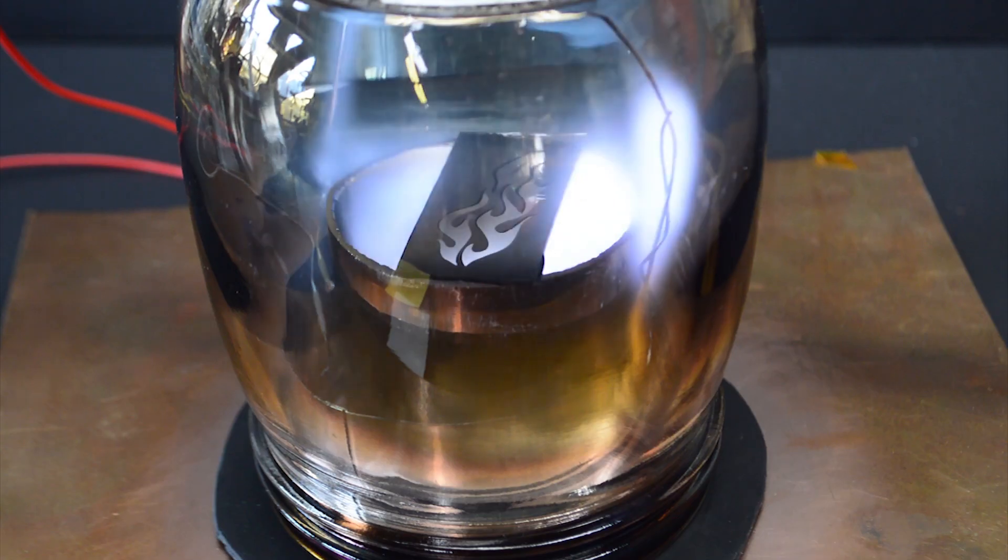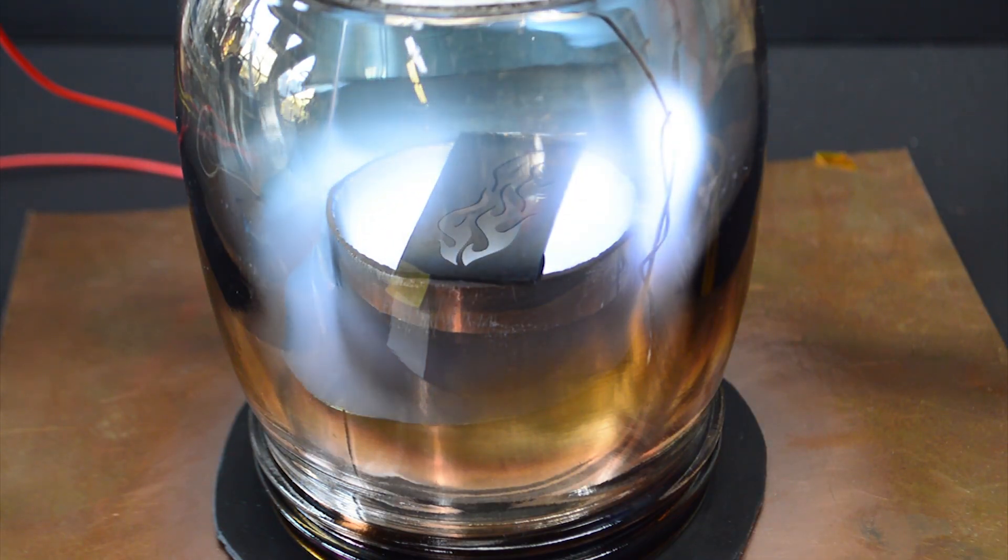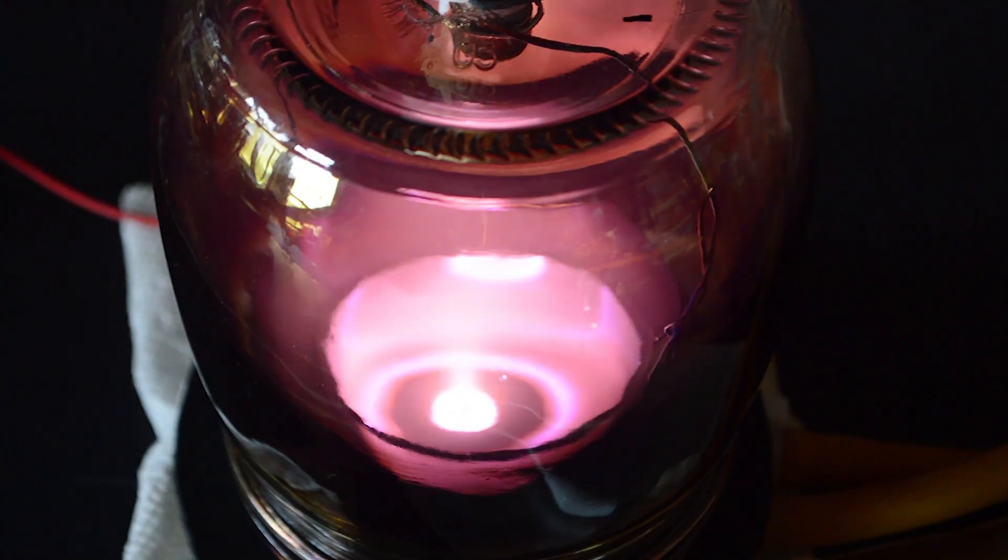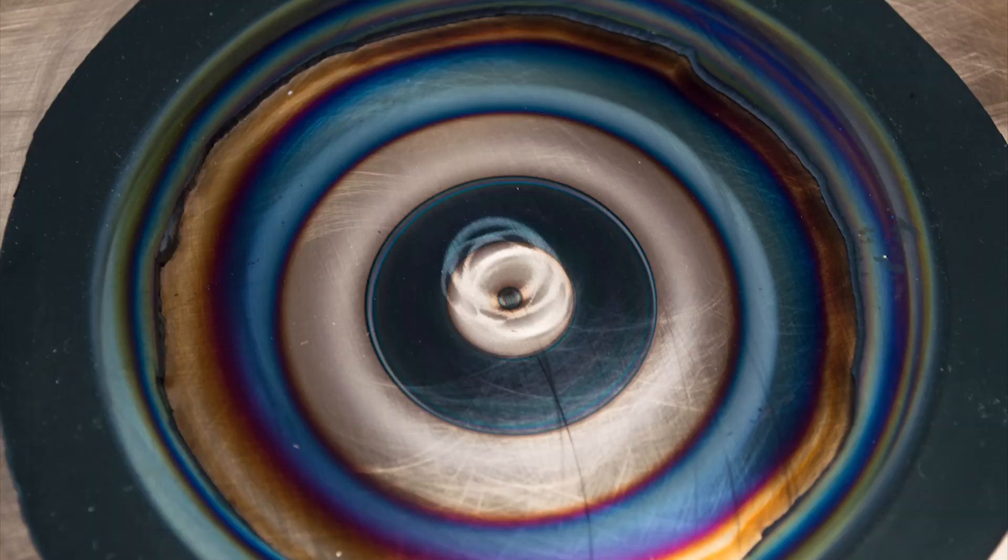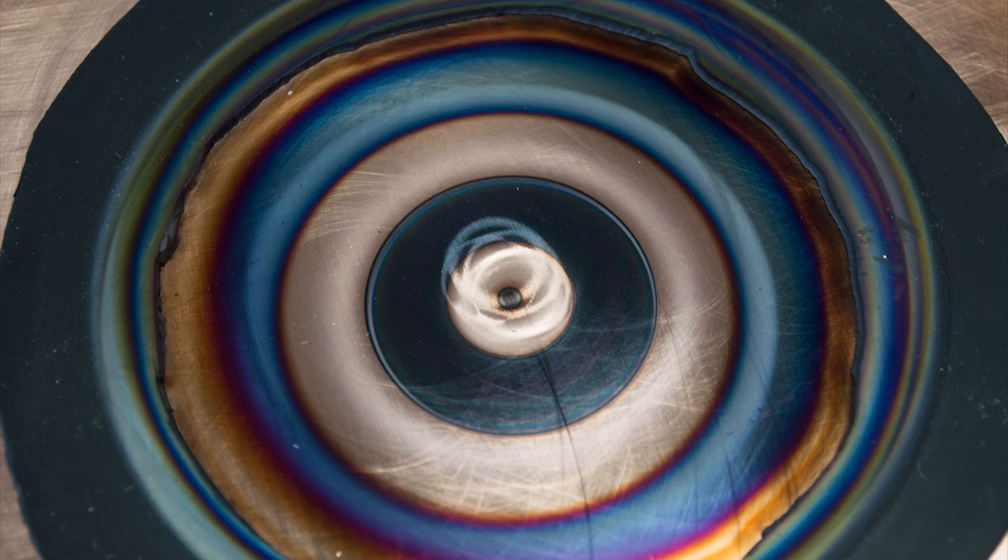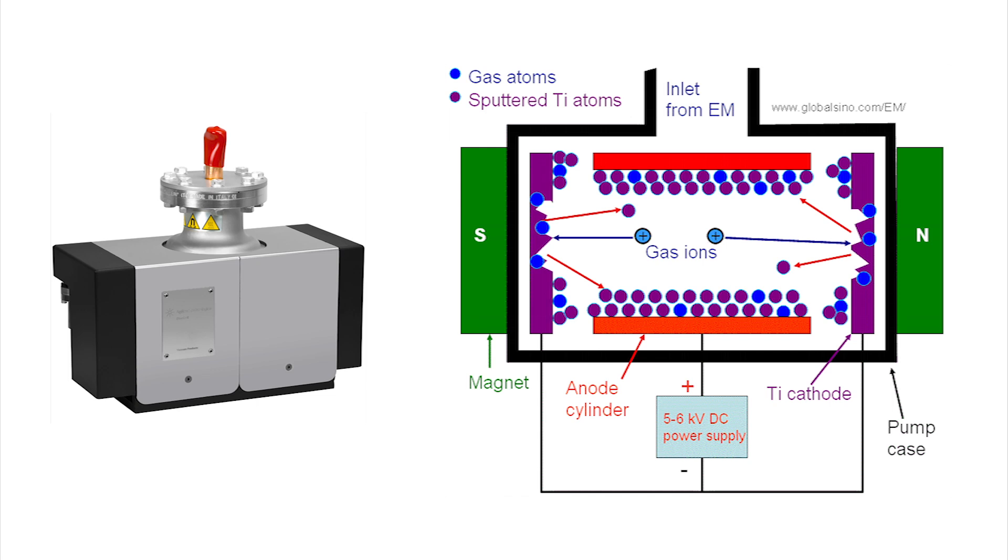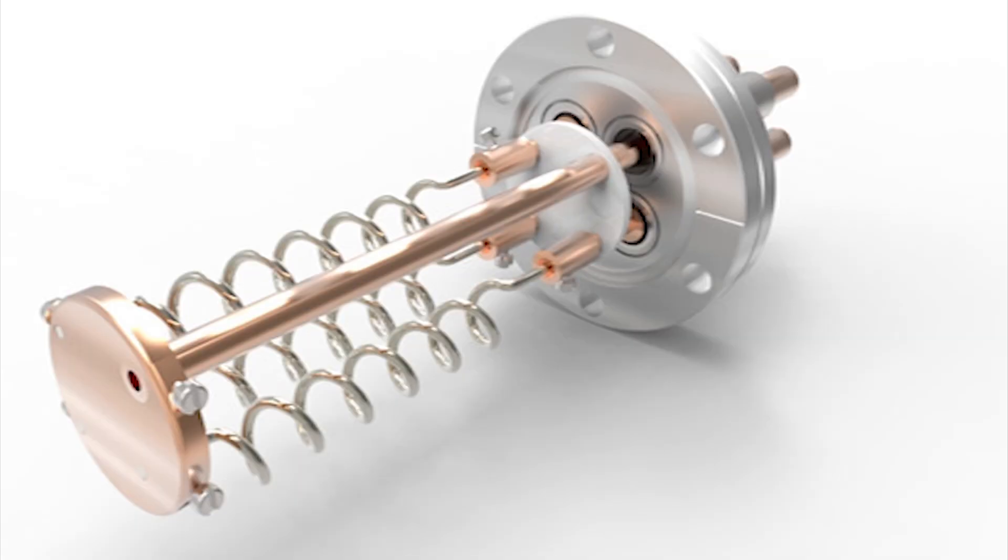Part of what's happening is that when the power is on, gas molecules are attracted to the base plate, and eventually you get too close to the magnet and are sucked into the hot plasma area. At this point they get accelerated at the base plate and crash into it. Especially for reactive things like copper or titanium, the molecules react with the metal and then stay put, so the pressure in the chamber drops as there's now less stuff floating around. There are actually special pumps called ion pumps that do this on purpose, and can pump up to many liters of gas per minute for really big units. But eventually new contaminants overwhelm this effect in my system. Another option is to have a secondary chamber that literally just sprays titanium at the walls, which will rapidly react with anything in the chamber and act as a remarkably good vacuum pump with no moving parts.